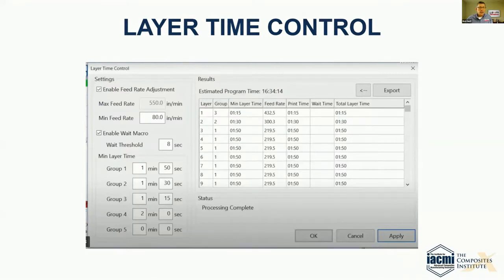What's really cool about this is you can set up a material parameter library for the material that you're depositing so that you have parameters built in on how fast the layer needs to be and what sort of methods you can use to slow down or speed up, whether you go to a minimum deposition speed, and then if you have to go slower than that, you stop between layers. This can all be programmed in. And what it makes for is a really easy process for 3D printing. A lot of the difficulty that was included in some of the earlier machines has been eliminated.